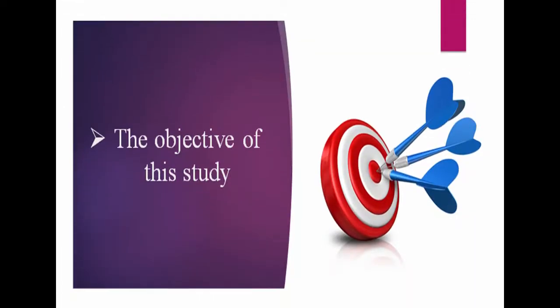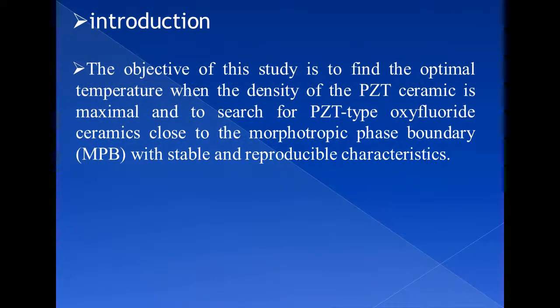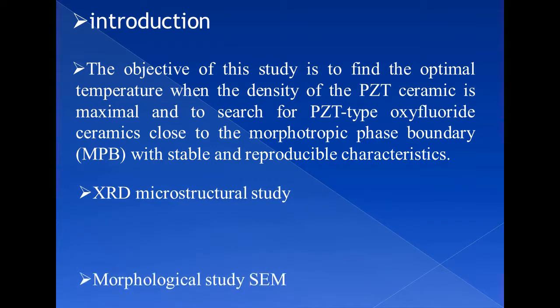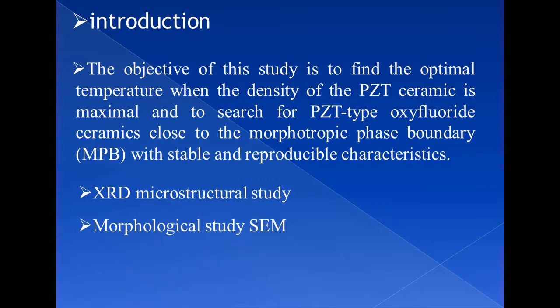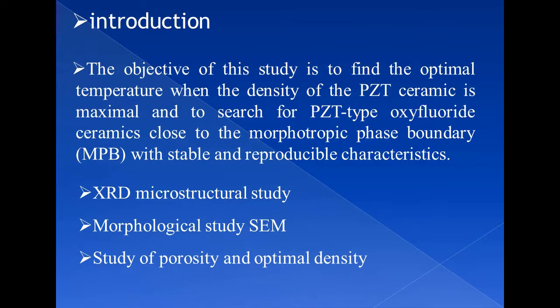The objective of this study is to find the optimal temperature at which the density of the PZT ceramic is maximal, and to search for PZT type oxyfluoride ceramics close to the morphotropic phase boundary with stable and reproducible characteristics. And we will add an XRD structure study, a morphological study by SEM, and a study of porosity and optimal density.